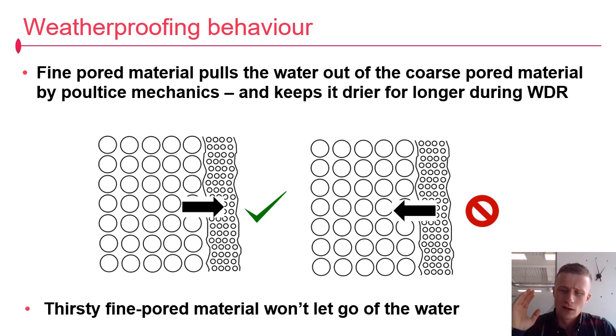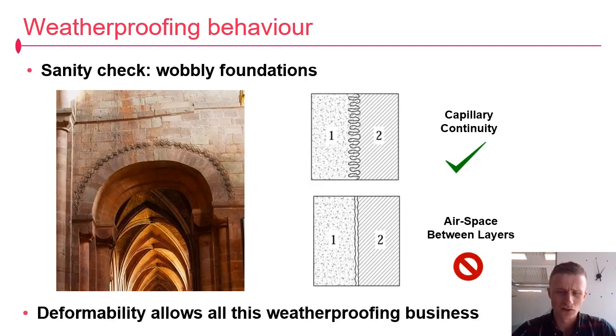If you cover a coarse pored material with a fine pored material, the fine pored material is the one that's getting wet, and it doesn't want to let go of the water into the coarse pored material by those same poultice mechanics. So it's right at the front of the material when the wind keeps blowing but the rain stops, ready to dry back out. So harling, the prime culmination of poultice principles, is key.